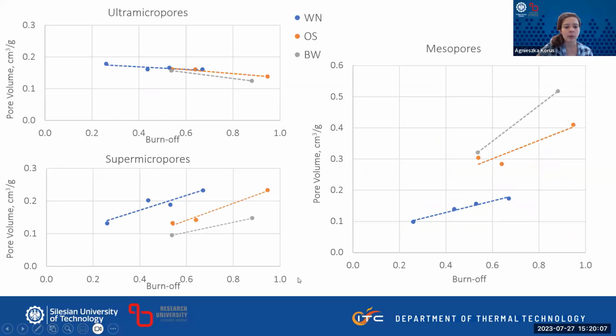And when we compare them with the walnut shells, the trends are similar: the decrease in ultra microporosity and increase in other pores. Interestingly, there was a different ratio of super micropores and mesopores. The walnut shells were yielding rather super micropores in the char, and the other samples actually went all the way to mesopores.